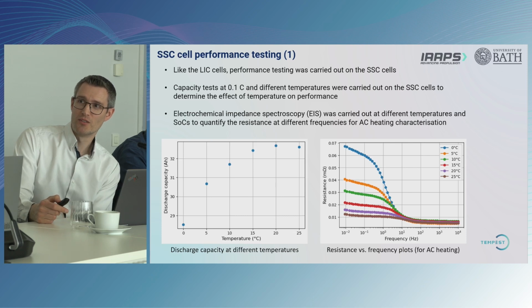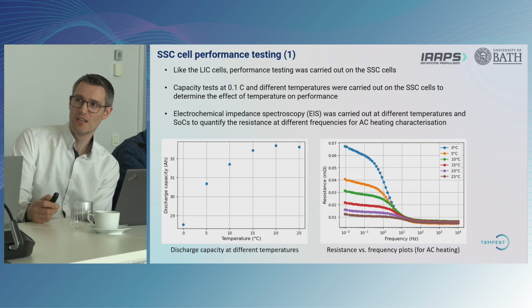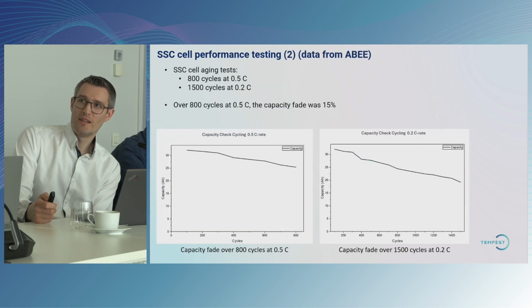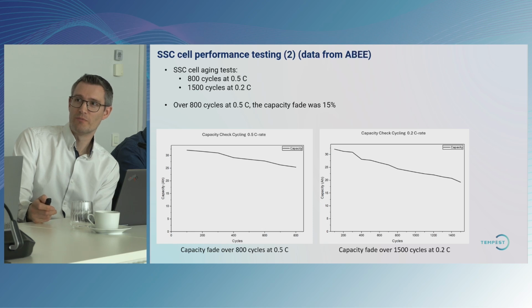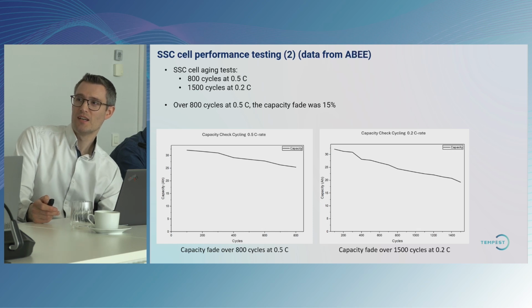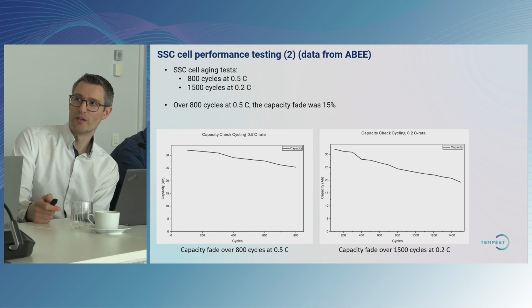And so we found really interesting results and demonstrated that actually with a relatively small amount of heating, just raising it from 0 to 5 degrees, we already get a huge increase in the available capacity and reduction in the internal resistance. And again, going up to 10 degrees, we get another sizable drop. ABEE conducted some aging tests themselves, and they demonstrated 85% capacity retention over 800 cycles, operating at half C, and considerably longer, over 1,500 cycles when running at lower C rates.